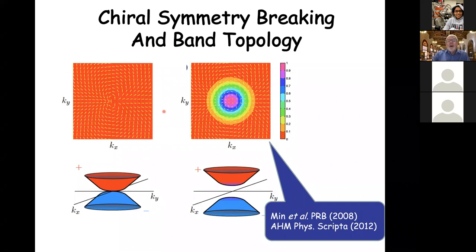And so bilayer graphene has a broken symmetry state where the pseudospin direction spontaneously twists out of the plane indicated here near zero momentum and goes to the North Pole, which corresponds to polarization in one of the two layers. That polarization is indicated by the color scale here. Along with that broken symmetry, it turns out, the gap between the valence band in blue and the conduction band in red opens up. So these are all properties of bilayer graphene that were explored some time ago, and are actually very fragile. In fact, this broken symmetry only occurs when interactions are made stronger by suspending a bilayer graphene sheet and removing the surrounding dielectric material.